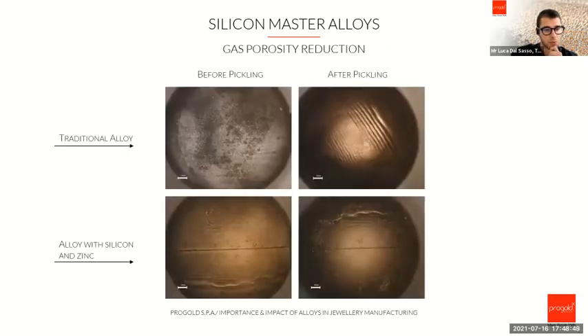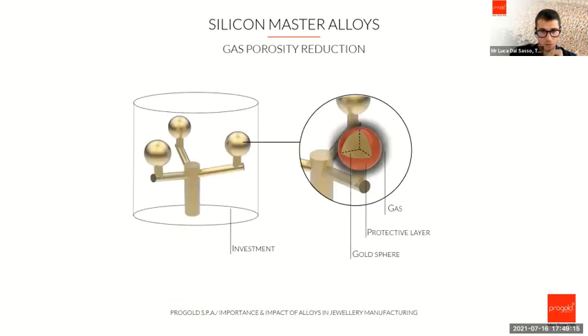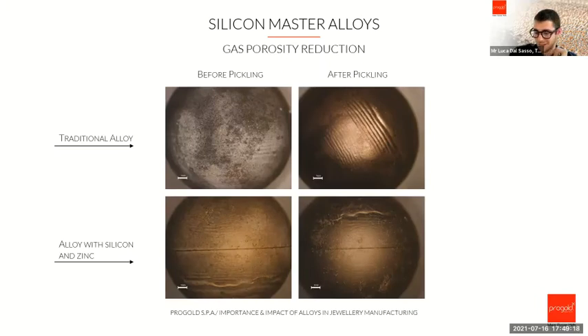So we can see a real example of it, because of a traditional alloy compared with an alloy with the silicon added. Once added to the zinc, the silicon creates this protective layer. Excuse me. And you can see the huge difference between the traditional alloy on the right and the gas alloy. Excuse me, this is my fault. The mouse is so sensitive. So, preventing also the composition of the investment that can release gases, silicon is really helping to reduce this defect in our alloy. So,